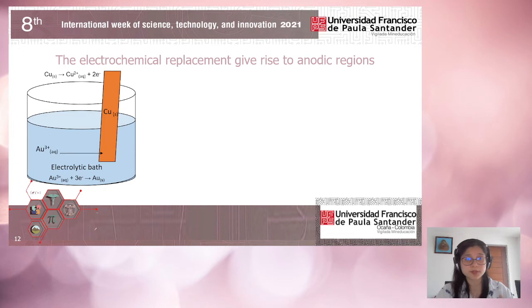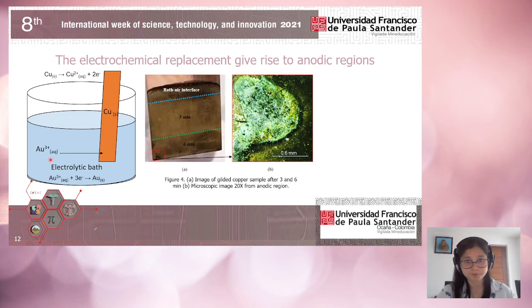The electrochemical replacement gave rise to anodic regions because of the replacement reaction itself. The gold ions were in the electrolytic bath, and for them to reduce and to gild, the copper needed to oxidize. This reaction has a limit. When all the surface of the copper has been oxidized and covered by the gold, then the reaction cannot proceed any longer.